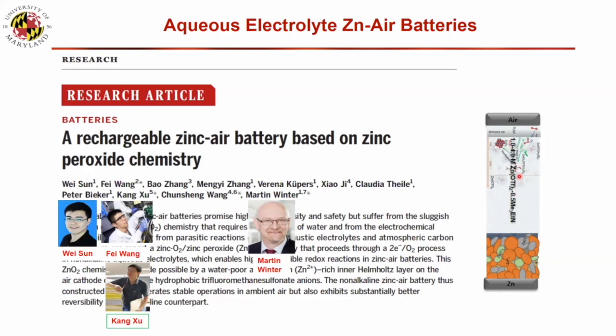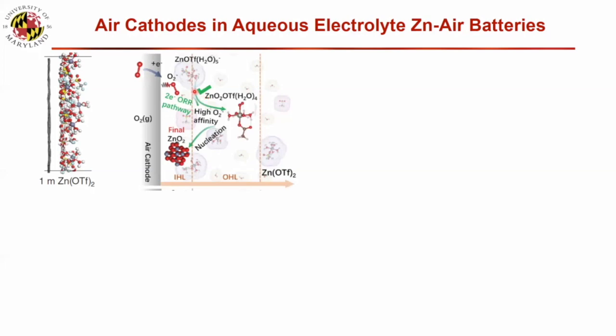Also, if we put a hydrophobic OTF salt, when charging, they can block the water in the cathode side. And then water is not involved or less involved in the oxidation reduction reaction, so they can go through the two electron reaction. So this is the idea. And hydrophobic OTF, when you have a charge on the cathode side, they block the water. And then the water is not involved in the reaction, and then they can easily form zinc oxide, zinc peroxide. This is the reaction.